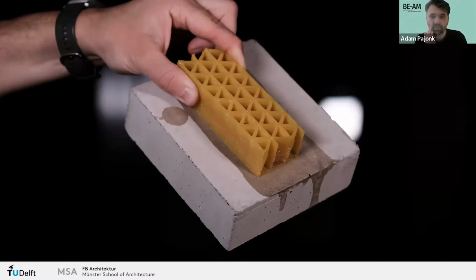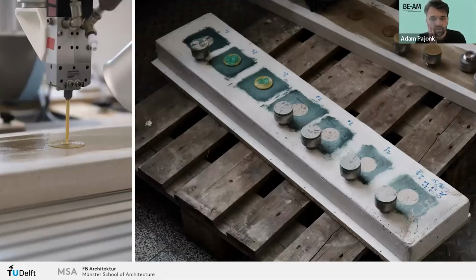On the topic of printing on top of a surface, polyurethane also provides strong adhesion. So we tested printing directly on top of an object, such as these concrete elements. And we even looked a little bit further into this and conducted an adhesive tensile test. With this test, we achieved an average of 1.63 Newton per square millimeter of tensile strength. Or to put it in another way, we could hang 326 kilogram of load on one of these testing stamps, which has a diameter of 50 millimeters.